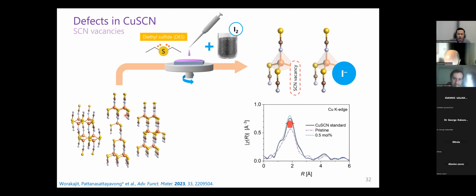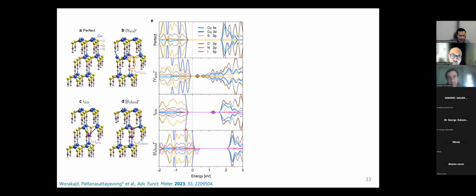And I think it's also possible. The porosity allows the hydrogen to diffuse through the material, and I think there are not just thiocyanate vacancies, but also copper vacancies inside as well. So I think any of the incomplete bonds would be active sites for hydrogens to interact.